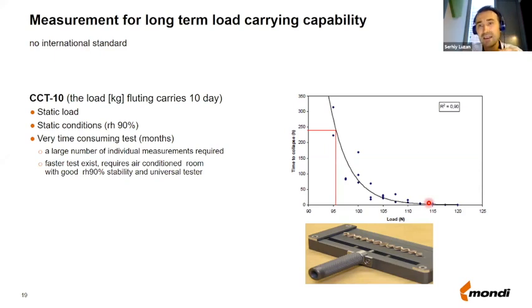And then, for instance, if you would like to find out what kind of paper you need to pick that will hold, for instance, 10 kilos or 100 newtons for a given time, you can use this curve to find out. In this case, 100 newtons or 10 kilos will be held by the paper for about 70 hours. So you can really understand what the lifetime of your paper will be, and what the lifetime of the box will be.